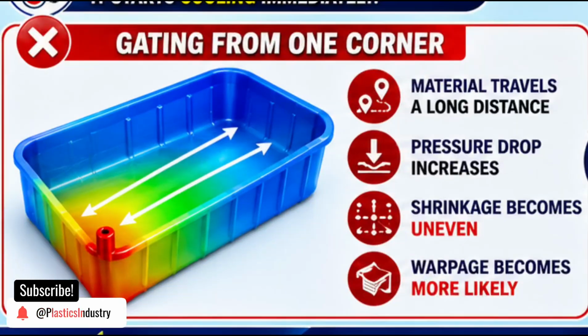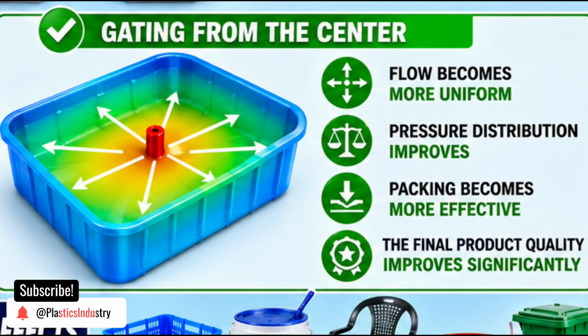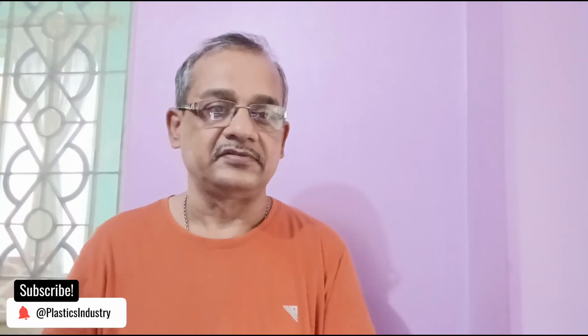Consider a rectangular container. If gated from one corner, material travels a long distance, pressure drop increases, shrinkage becomes uneven, warpage becomes more likely. Now imagine gating from the center. Flow becomes more uniform, pressure distribution improves, packing becomes more effective, the final product quality improves significantly. This shows why gate location directly affects product performance.